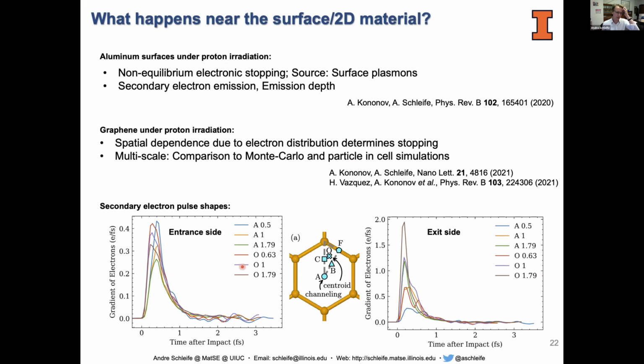I want to show you the currently recent interesting preliminary data we found, which is the pulse length and pulse shape of a secondary electron pulse that you get when you shoot the proton through the material. We can compute that now after we implemented absorbing boundary conditions in our TD-DFT code, and we see that the entrance side and the exit side show actually a different dependence of the secondary electron pulse shape on velocity.